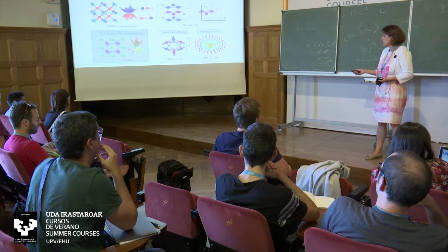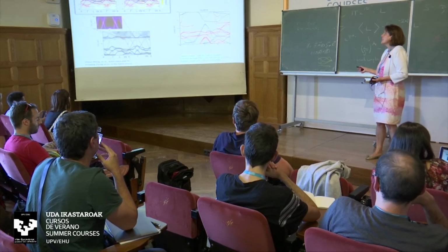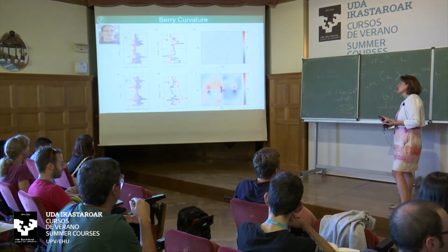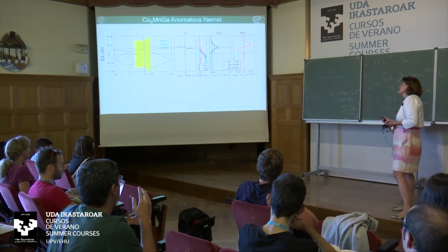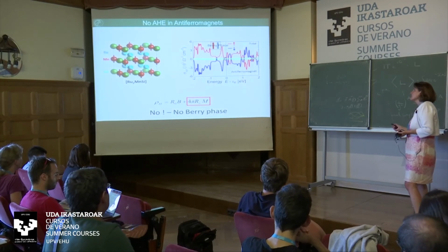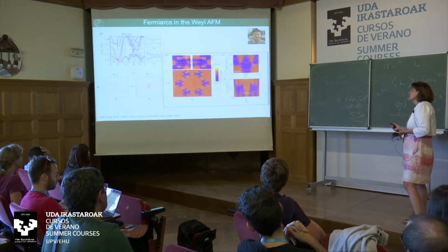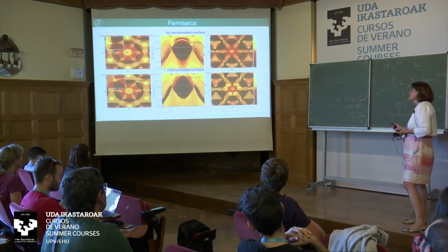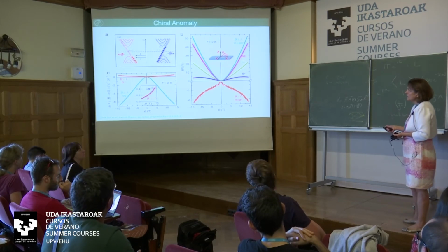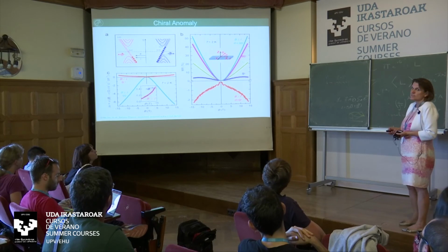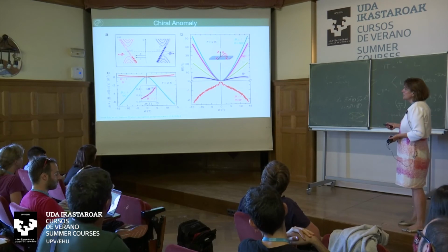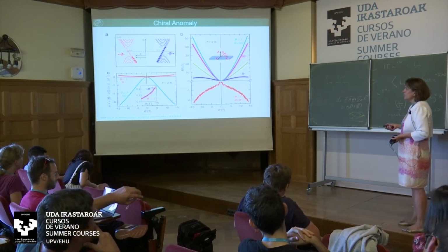In this cobalt 3 tin, it's not so large as we have, for example, in mercury telluride or some other materials. But it's similar to other systems where people measured in magnetic systems, for example manganese 3 tin; they have a similar order of magnitude. You see the magnetoresistance is not like in niobium phosphide, where we have a magnetoresistance of 100,000 or a million. But because of the spins and the scattering, I assume we never get such a high magnetoresistance.